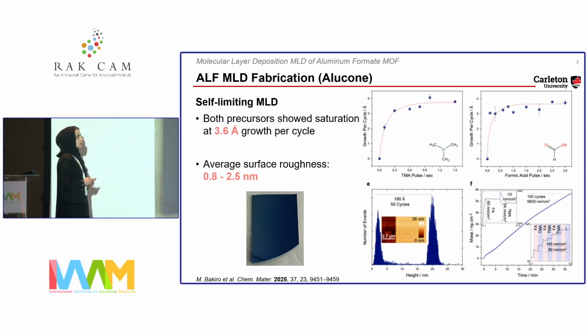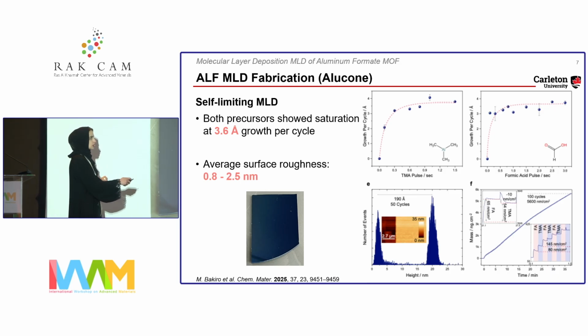The way we measure the thickness here is by atomic force microscope, with which we deposit the thin film, that is this thing here. We deposit it, and then we scratch the surface. And then with a needle, the atomic force microscope goes across that scratch, and from the imaging process you can see the height distribution at the silicon side and the height distribution at the thin film side. And the distance between those two tells you what the thickness of the film is. So we're using this in order to generate the saturation curves.